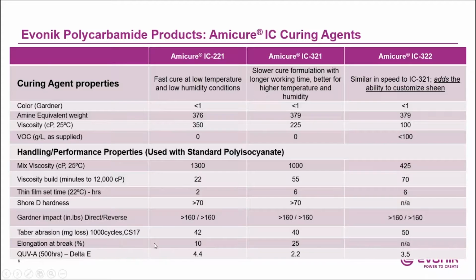Tensile elongation at break, the reason we show this is that these do have some flexibility. Again, a lot of times with epoxies, they do have high tensile strength, they have high hardness, but generally the elongation is very low, but these do have some flexibility, as you can see here in the numbers. Finally, UV resistance. As I mentioned, these are light stable systems. So you can see the accelerated aging testing, delta E, these are very low. That means, again, these have very good UV resistance and can be used for indoor or exterior application.